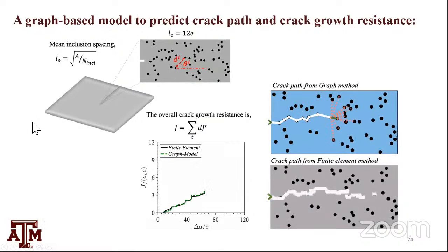This is an evolving graph. Every time I know my crack tip, I build my graph, or a bunch of vectors, and I pick based on the criteria we define. We get a very reasonably close crack path predicted from the graph model as the finite element calculation. And we also get very nice correlation in the overall fracture toughness.